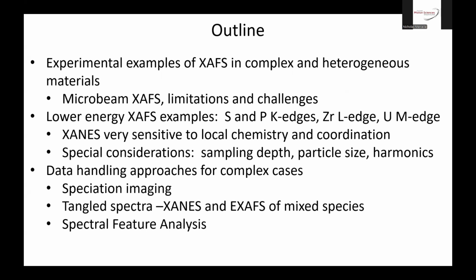So I'll describe some examples in complex materials, primarily by using microbeam XAFS. So we're looking at smaller subregions of samples, and also lower energies for sulfur and phosphorus. For the lower energy elements and lower energy edges, these edges are more sensitive to the local chemistry and coordination. The energy of the electrons is closer to the valence electron energies. So it's much more sensitive to what's going on around an atom than the harder X-rays. But there are special considerations for doing these experiments.